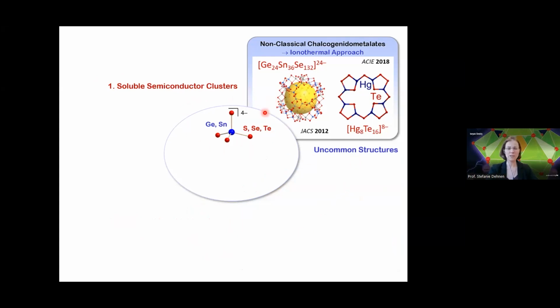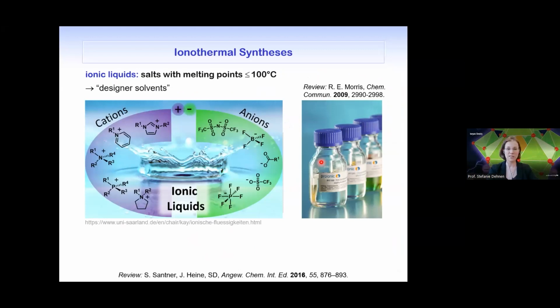So as I told you, we can use these precursor molecules and put them into ionic liquids to do the so-called ionothermal approach and find very uncommon structures. And we use either these small tetrahedra or we use larger ones, so-called supertetrahedra, as precursor materials. So you'll see a little bit more than just these little tetrahedra today. And we use ionic liquids for it. Ionic liquids are just salts with very low melting points, like below 100 degrees C.